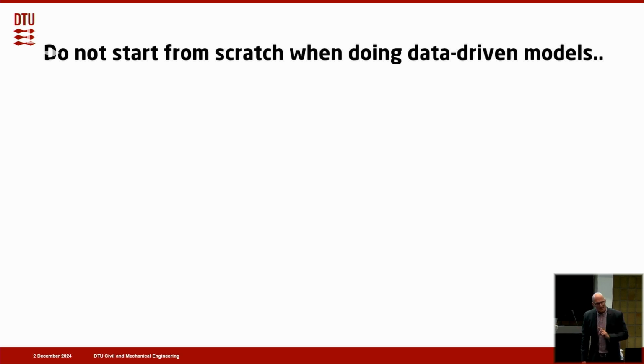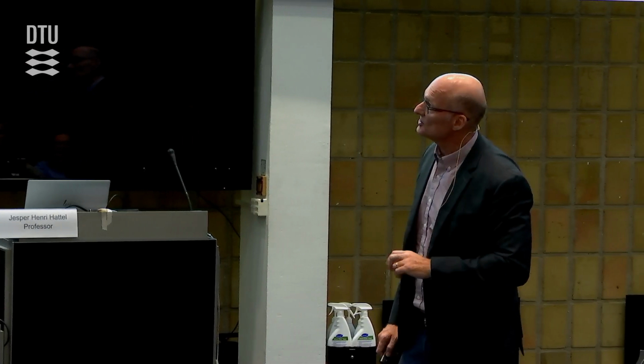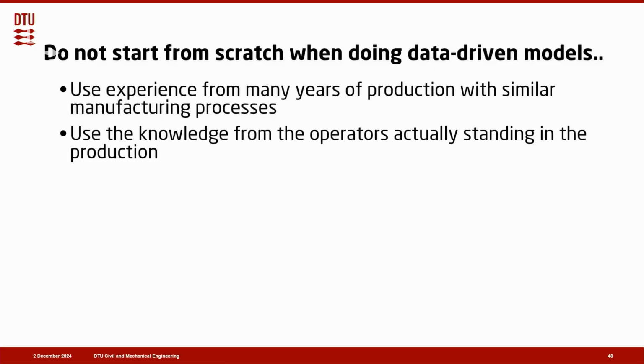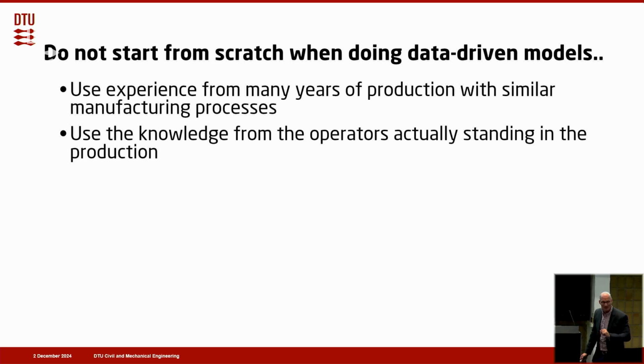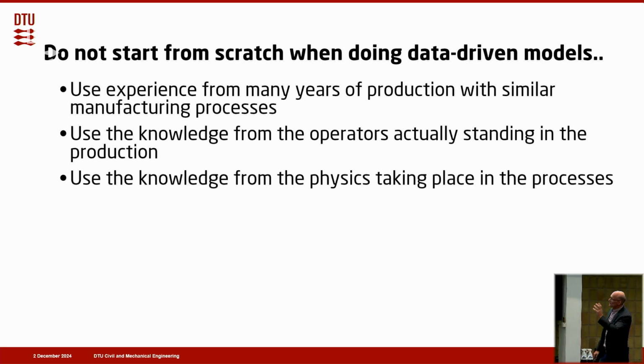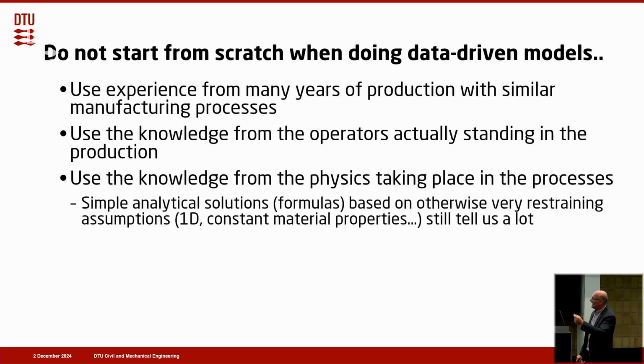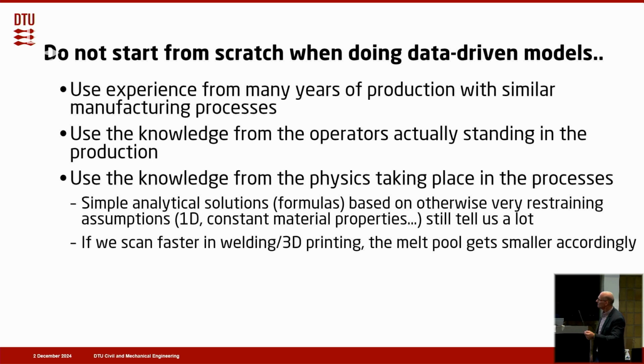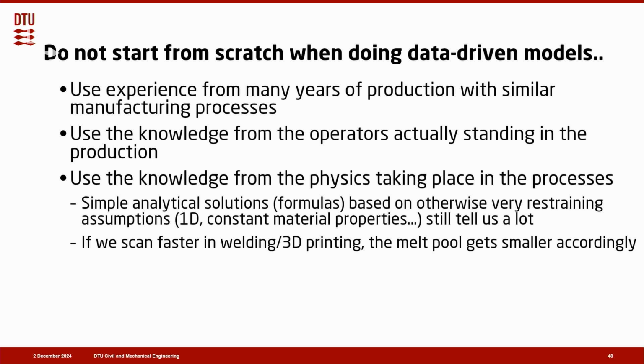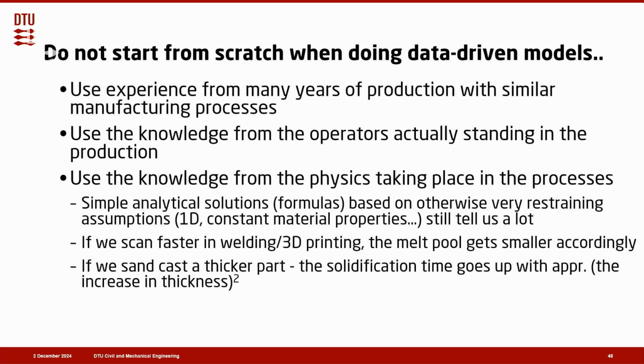And when you do data-driven models, you should not start from scratch. You should use the experience from many years of production. You should use the knowledge from the operators actually standing in the production. That is really important. And you should use the knowledge from the physics taking place in the processes. And this could be simple analytical solutions based on otherwise very restraining assumptions: 1D, constant material properties, blah, blah, blah. But still they tell us trends. So we don't look for the needle in the haystack without an expectation. For example, if we scan faster in welding, the melt pool gets smaller. If we sand cast a thicker part, the solidification time goes up with approximately the increase in thickness squared. Something like that. These are simple expectations that our data at least should show something that reminds us of.